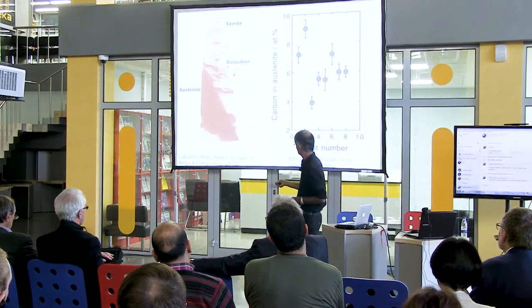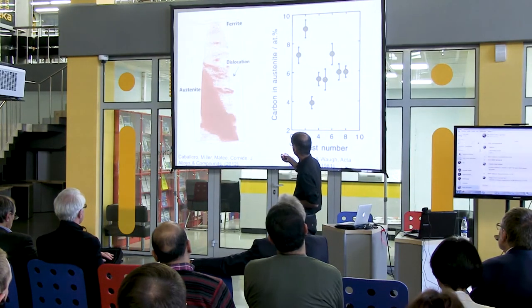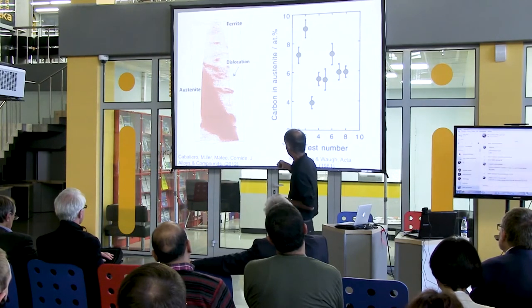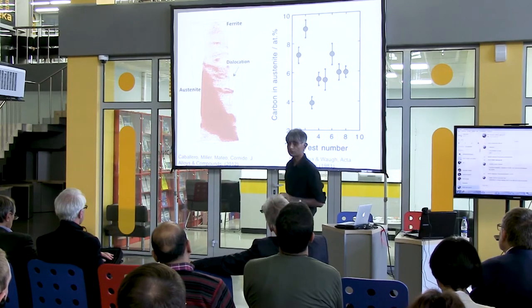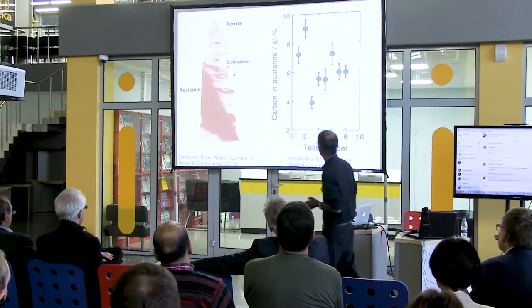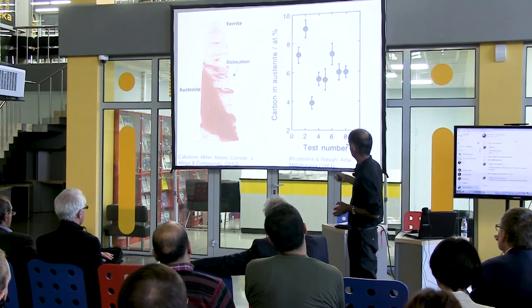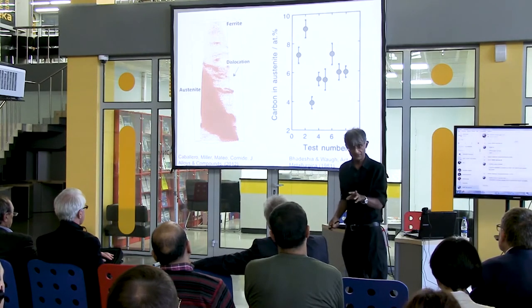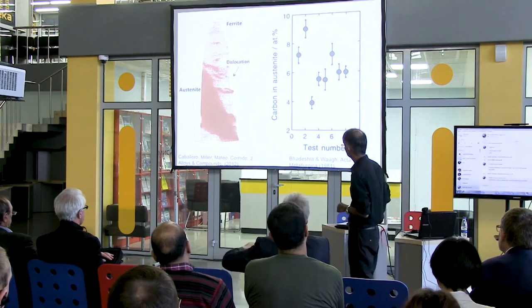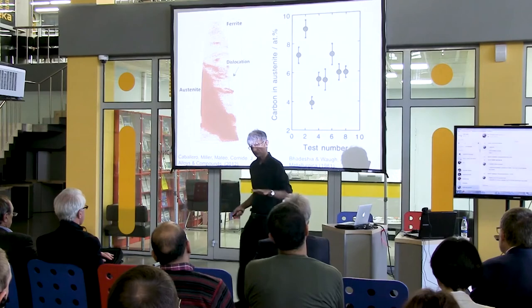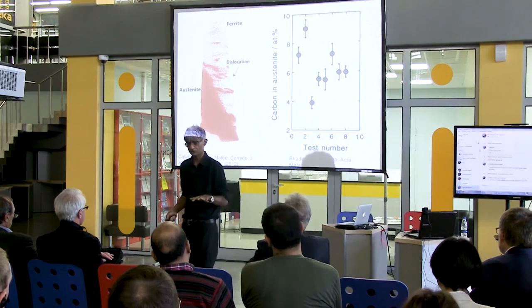This is from Bhadeshia's book, where you can see the distribution of carbon atoms in the ferrite and in the austenite, which is much richer. You can also see carbon atoms at dislocations because they are attracted to dislocations. You can make measurements at different locations in the austenite and find that the concentration on that scale is not constant. Once again, we do not have a uniform distribution of solute in our material.